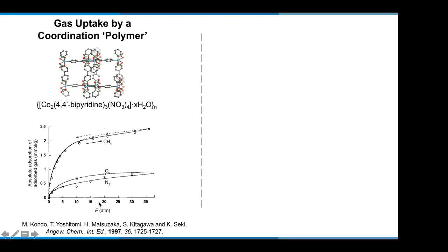Okay, this is not a gas adsorption isotherm. Any material, even a piece of cloth, when pressurized with gas will show gas uptake. So this does not prove permanent porosity. And this experiment cannot give you the pore volume or surface area because it's done under high pressure.